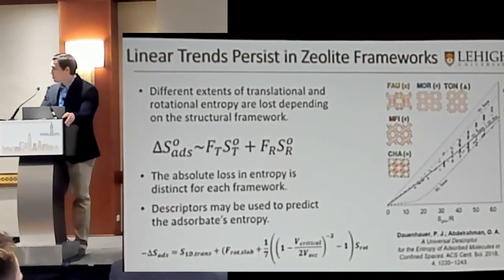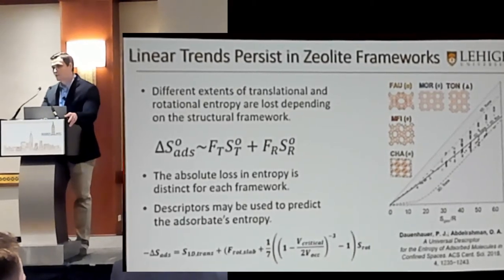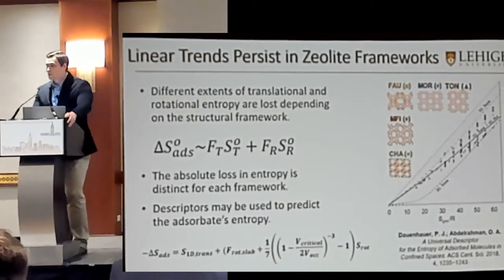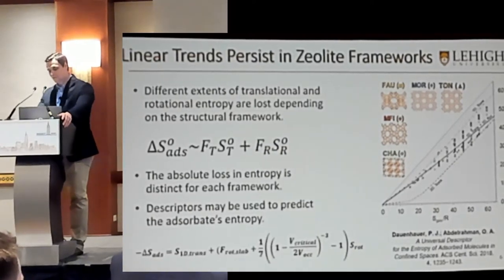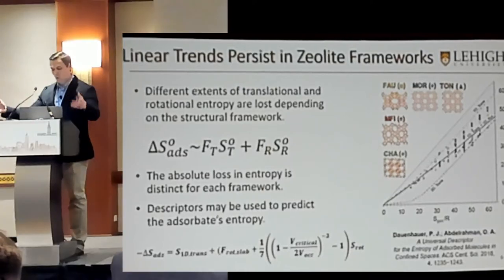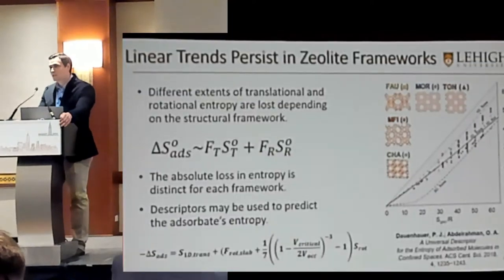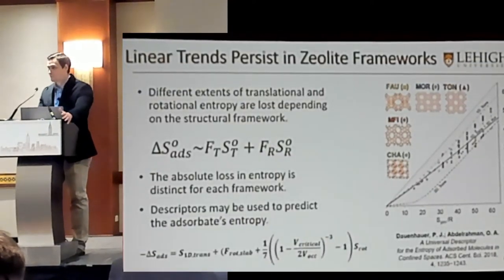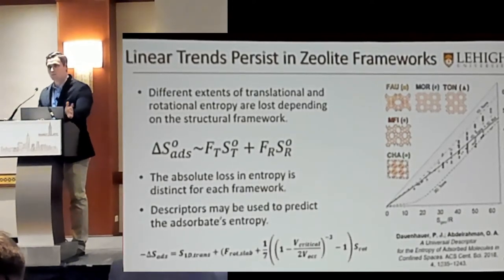But the slope was no longer just two-thirds as in the case of a two-dimensional catalytic surface — it now depended on the size of the zeolite. Namely, if we look at a faujasite, which is larger in terms of pore and occupiable volume than MFI, it has a larger slope, meaning that the molecule retains more degrees of freedom and has a larger entropy within the voids of a faujasite as opposed to MFI.